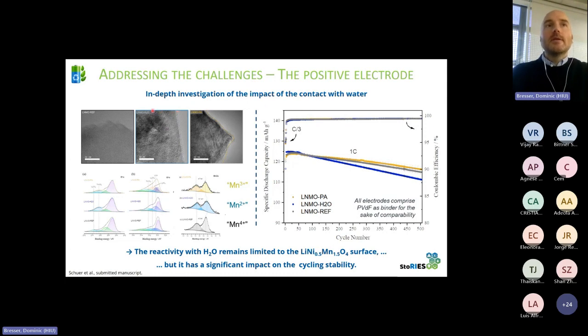So if we bring the LNMO in contact with water, then what we observe is the formation of this very thin amorphous layer, right? And we see that the manganese at the surface, not in the bulk, but at the surface, is reduced basically from 4+ to 2+. In fact, I did not mention, but when we did the neutron diffraction, we were also checking the reactivity not only with the water, but also with deuterated water. And we observed that there is probably some minor exchange, a minor fraction, of what is frequently reported for NMC type materials, this kind of lithium proton exchange. In that case, a lithium deuterium exchange.